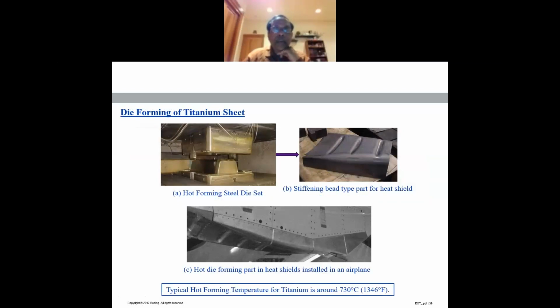As I mentioned, hot die forming is also another hot forming operation. That's a pretty heavy top and bottom die. There's an example of the hot die forming process. This is also part of the heat shield components, as you can see over here. I think it's for the 757, a very old aircraft. Typical hot forming temperature for titanium is 730 degrees centigrade, 1346 degrees Fahrenheit.